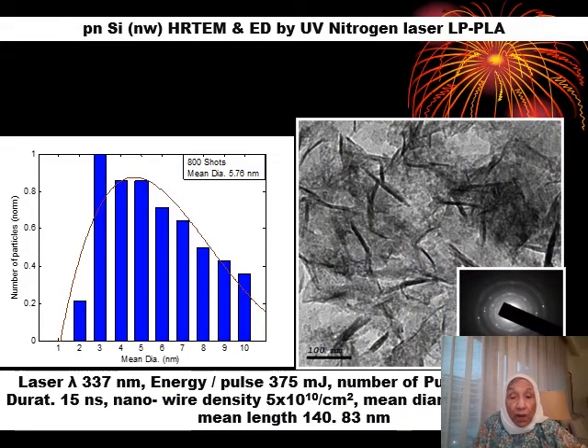And it peaks at 5.76 nanometer. This gives the mean diameter. But it was found to be not parallel, and the rods formed were haphazardly distributed in the sample, but the electron diffraction shows that it kept the crystalline structure.